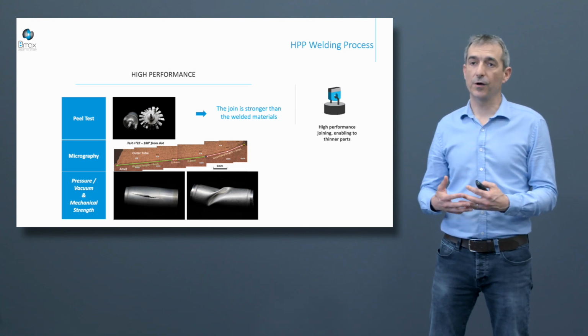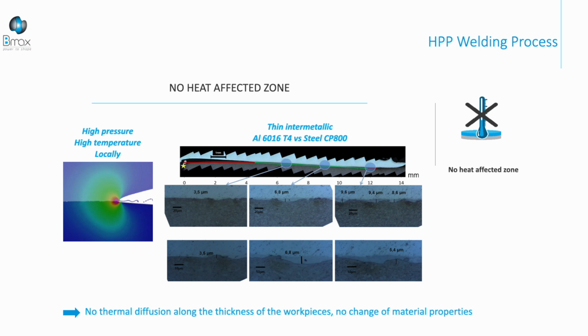Usually, the joint is stronger than the welded materials. We are not able to perform an end-to-end join. We always have an overlap between the parent part and the flyer, for example. No heat-affected zone. To perform magnetic pulse welding, we have to reach a very high velocity at the impact.